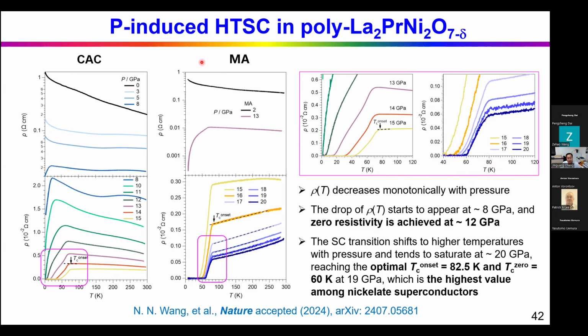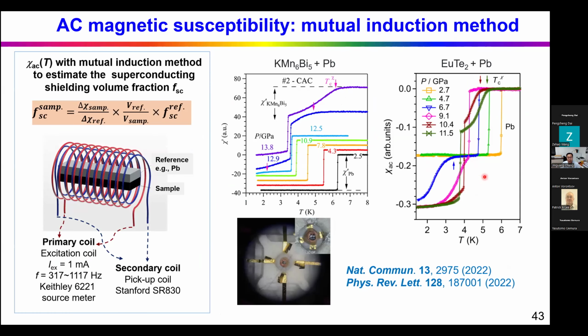So even though the praseodymium doped sample shows a higher resistivity at ambient pressure, it shows a better superconducting transition temperature in terms of the TC0. So we are very curious about this observation. After observing the zero resistivity, the next issue is: how about the superconducting volume fraction?